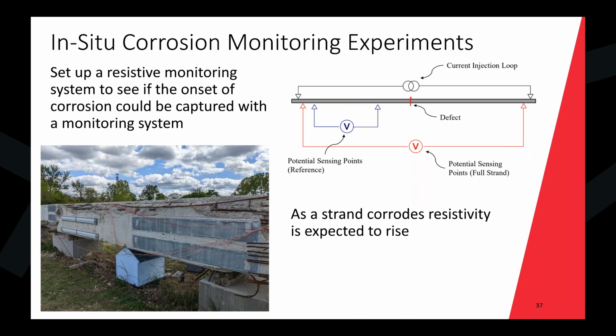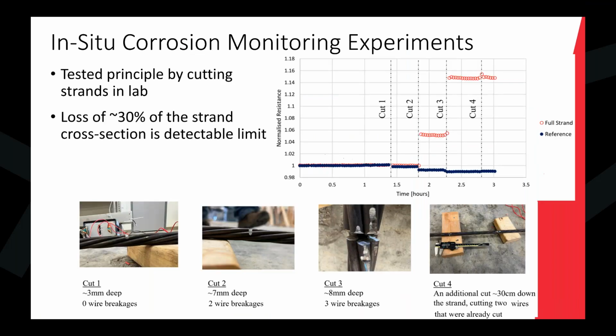And we tested this in the lab to give ourselves a baseline to understand what types of losses would be necessary for this type of measurement. We did this simply by taking a non-corroded strand and mechanically cutting it. So what you're seeing here is, cut number 1 is relatively small.